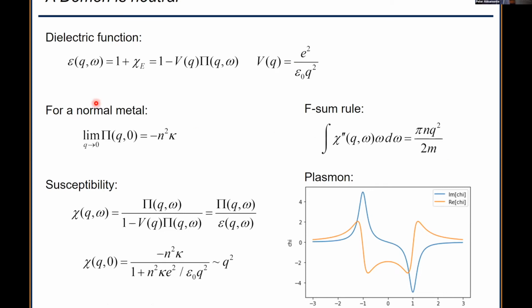So as you know, the normal metals screen charge, and this epsilon has to be infinite and diverges at zero frequency. And epsilon is related to pi, the polarization, which is determined by the compressibility sum rule to be constant in a metal at zero frequency in the low momentum limit. This is the compressibility sum rule. Because of this, the susceptibility in a normal metal has to go like Q squared at low momentum. And that in the normal metal, and I'm being somewhat mechanical here, is accomplished by the plasmon. And you can see it in copper, you can see it in graphite.